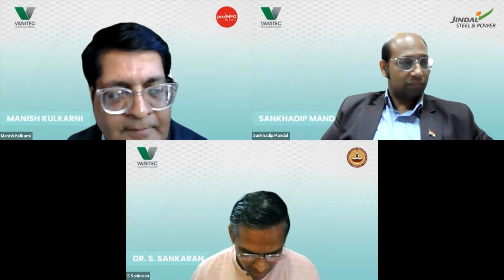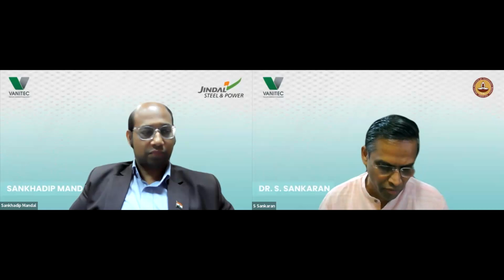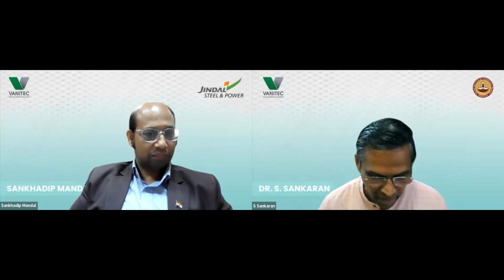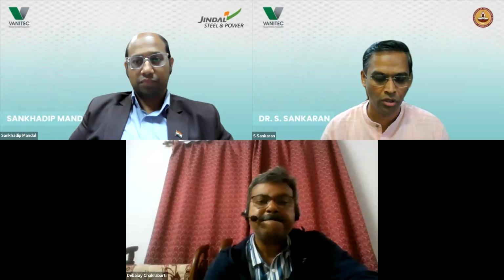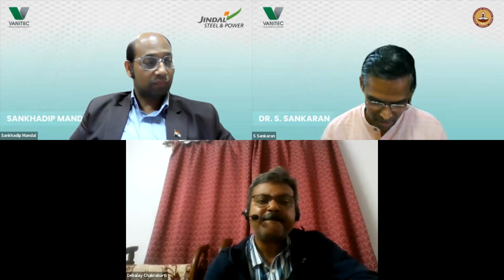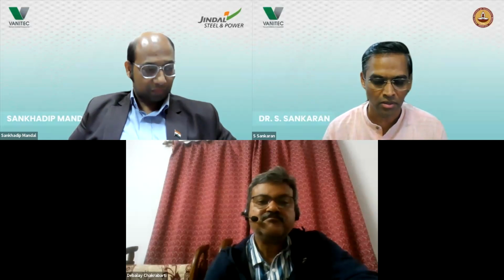Yes. So this particular question, we have done some experiments in our laboratory. For example, for producing ultrafine grain dual phase sheet, the chemistry is also HSLA. We were successful in achieving the required properties with a combination of vanadium and niobium. We tried severe cold rolling and some warm rolling combinations, and then we got the best combination of strength and ductility for the HSLA sheet. This we have done on laboratory scale. This is my experience. Over to Manish.